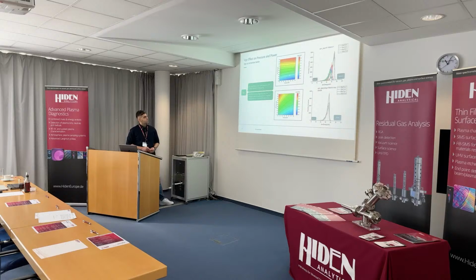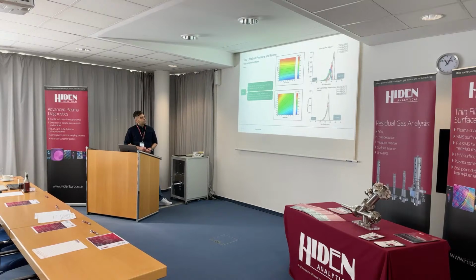So when we change the pressure for RF power at higher frequency, we don't see any change in upper VPP. But when we change the pressure for lower RF power, we saw differences in VPP. So it is a tool, it adjusts itself when we change the pressure. So to see the real pressure effect, we ran an experiment with constant VPP. So this is the before, constant power 300, and here is constant VPP. So here you see the real pressure effect: just a decrease in integral intensity, and the energies are constant.